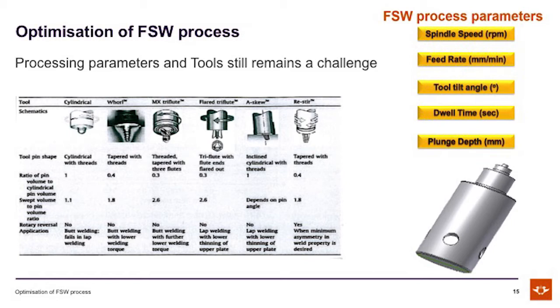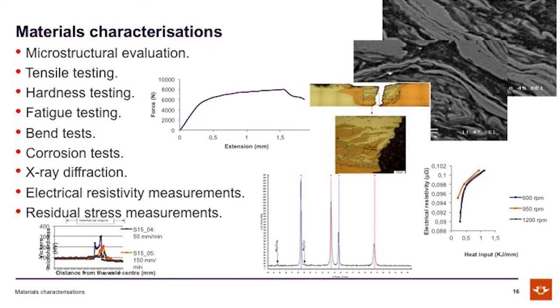And these I was able to achieve by using design of experiments to be able to achieve welds with good integrity. And when we conduct welds, we always want to ascertain the joint integrity. In so doing, we have to characterize the welds, either through materials characterization, mechanical testing, corrosion testing, XRD diffraction, electrical resistivity, or residual stress characterization, depending on the typical application that the weld is intended for. And these are some of the results for joining aluminum and copper.